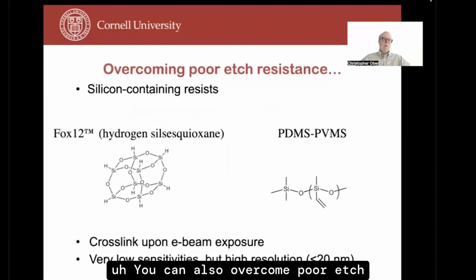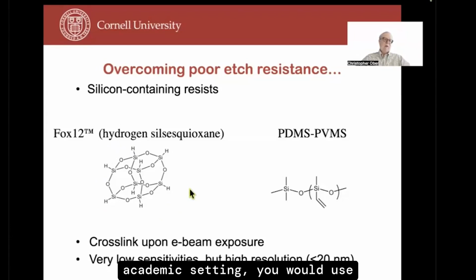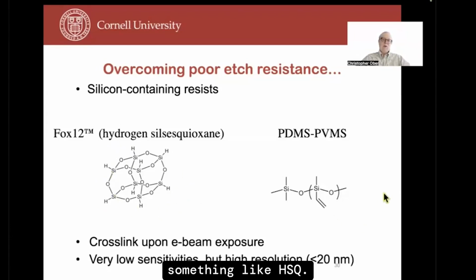You can also overcome poor etch resistance in these types of systems by incorporating silicon. And so silicon has been used in so-called HSQ resist materials. The batch-to-batch variability is fairly high. Reproducibility can be good or bad depending on circumstance. Moisture is potentially a problem. And yet for really very, very high resolution, so very tiny dimension features, in an academic setting, you would use something like HSQ. And this particular polymer also can make a negative tone system through cross-linking of these double bonds and counting on the silicon to have good etch resistance.